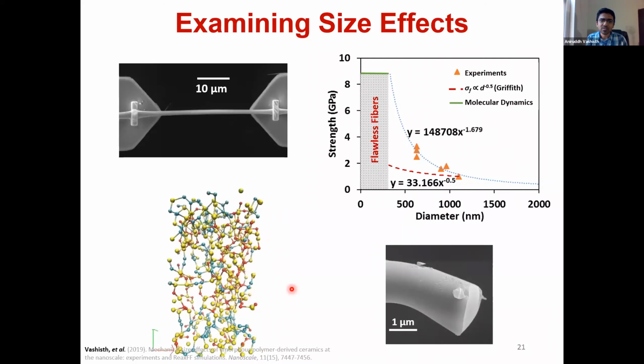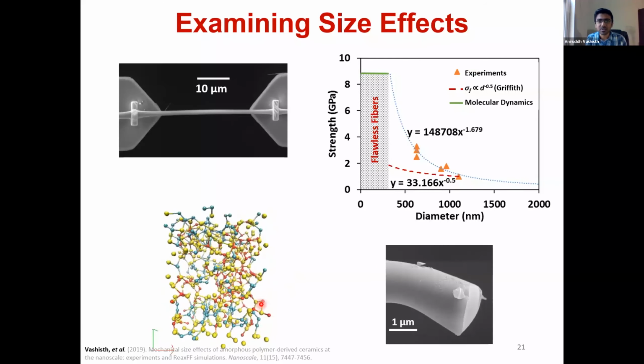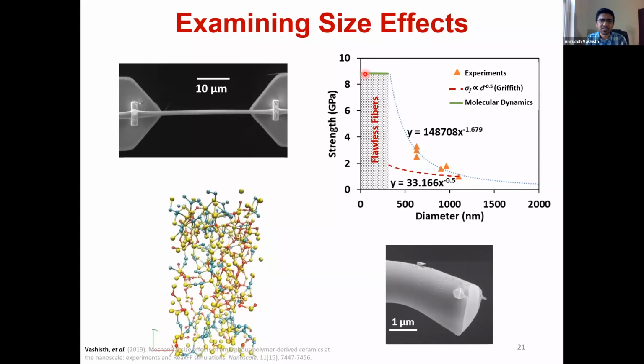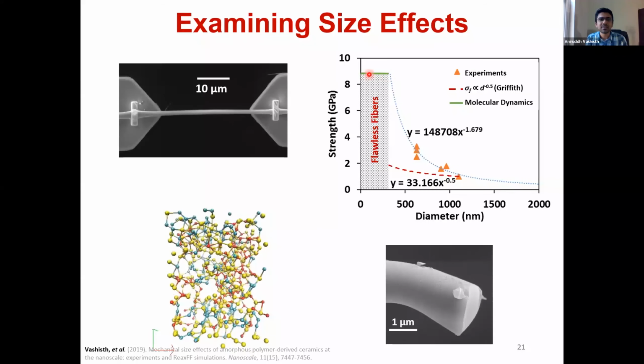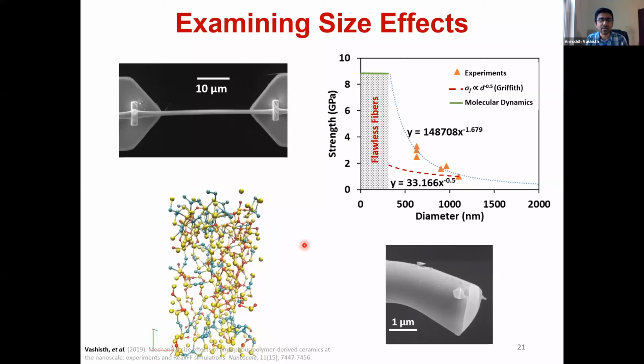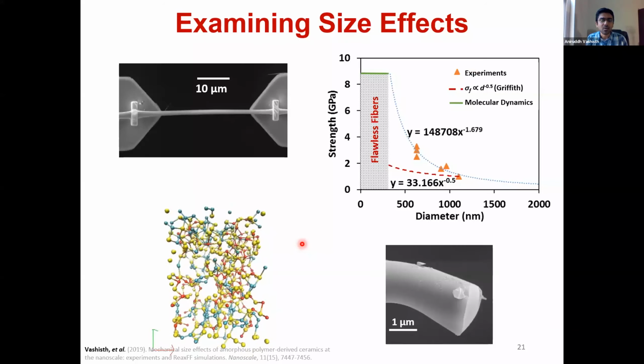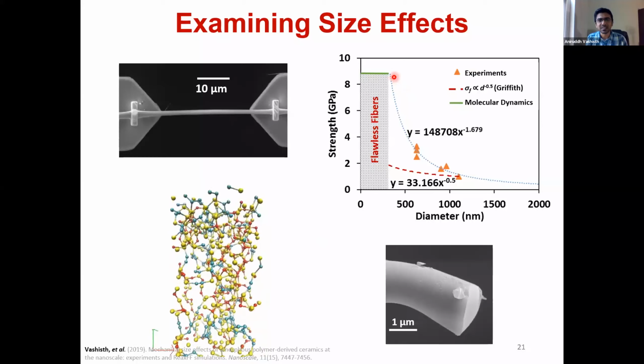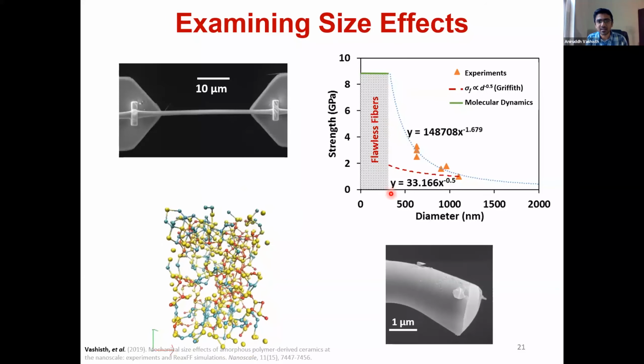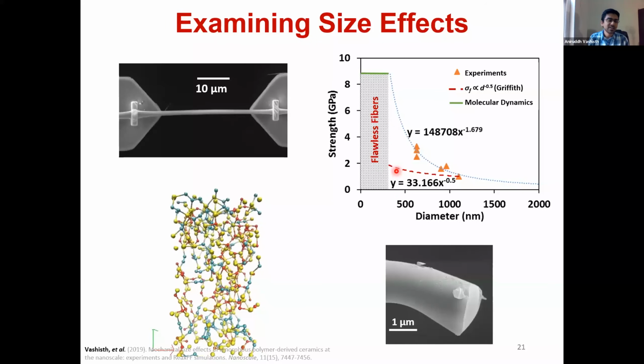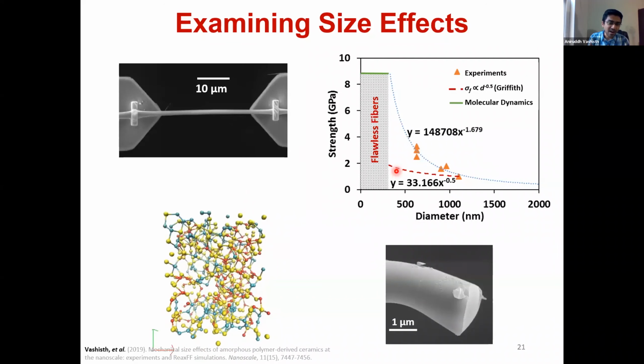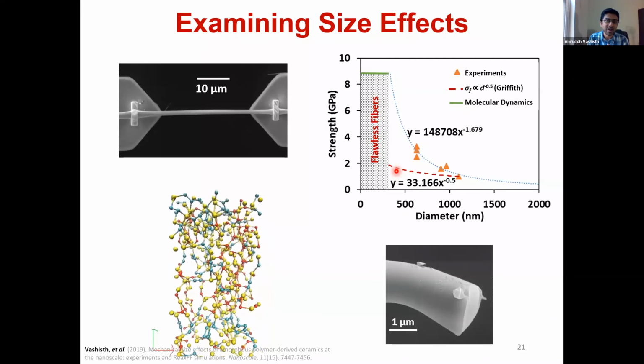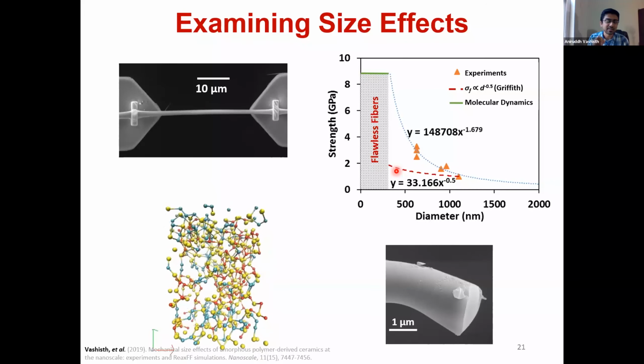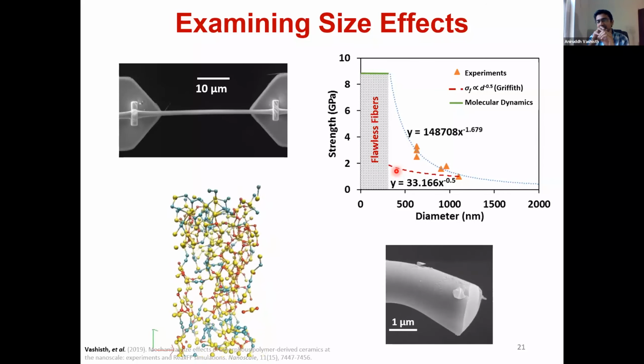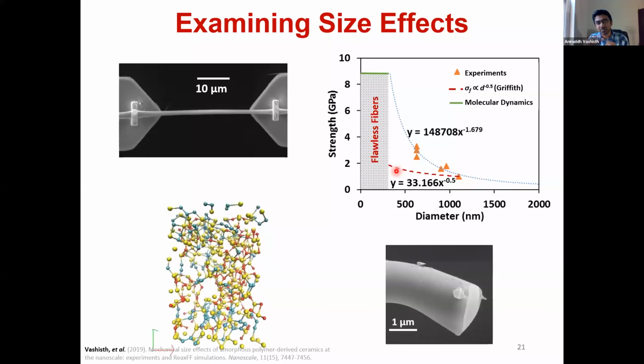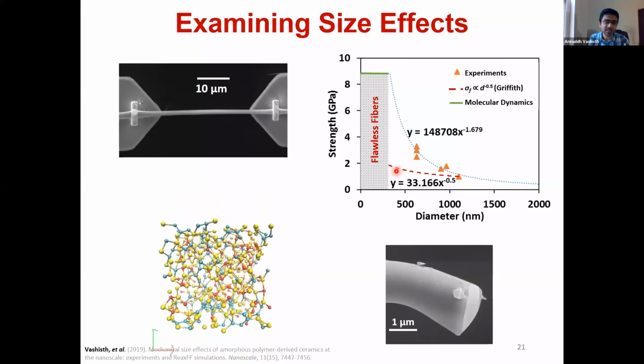So we carried out some molecular dynamics simulations of flawless materials. And we found that the maximum strength that could be achieved by these fibers is around 8.5 GPa. Now, when we extrapolate our experimental results, this actually comes out at around 330 nanometers. So basically what we figured out was that once you get to fibers of diameter 330 nanometers, all the gases are able to escape the fiber before the solidification starts, which is a very interesting observation.